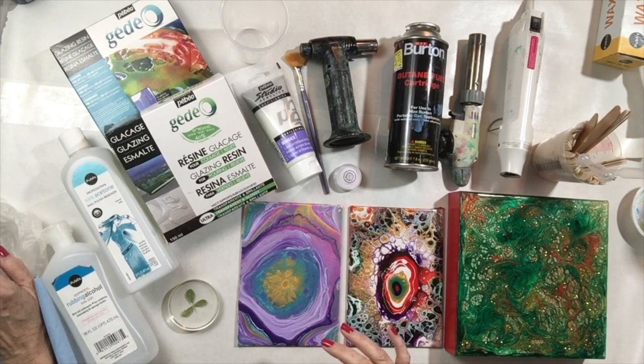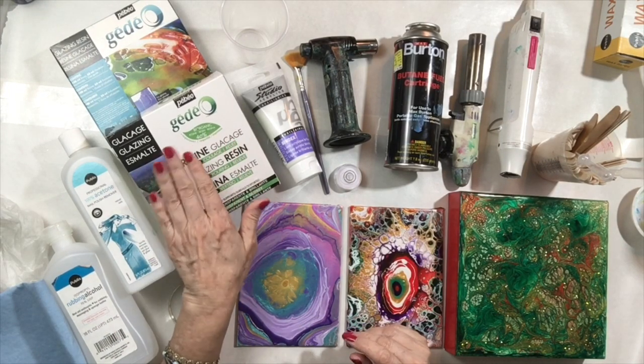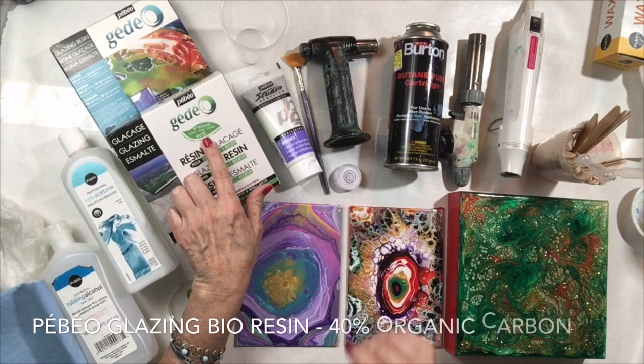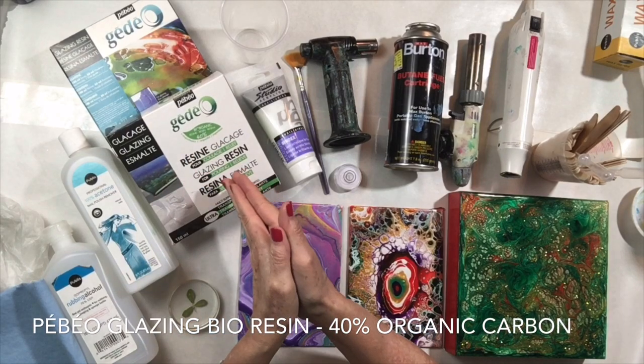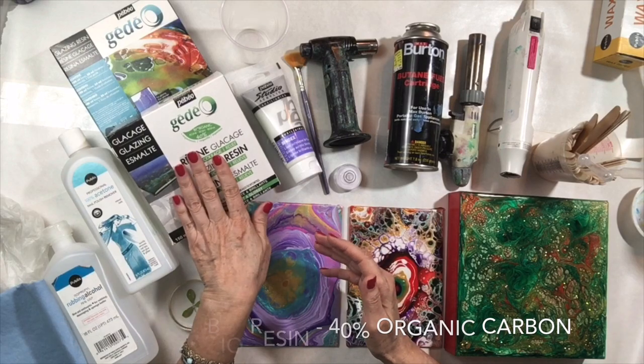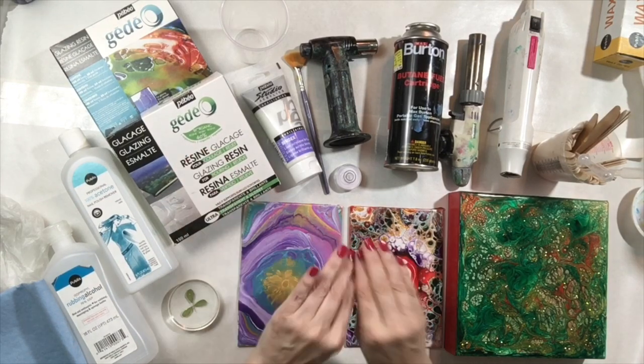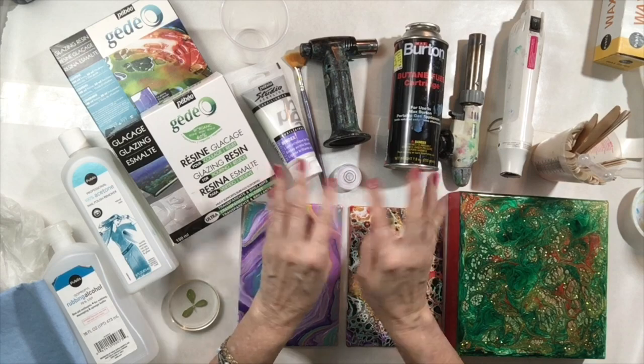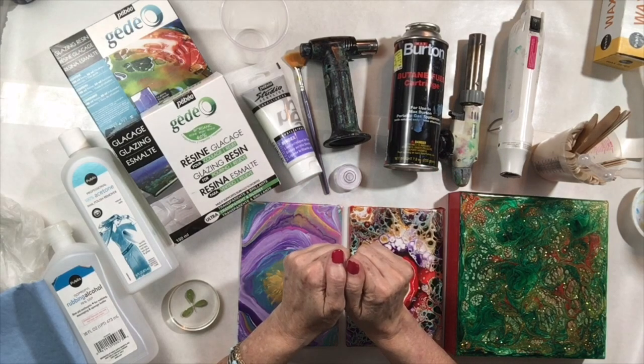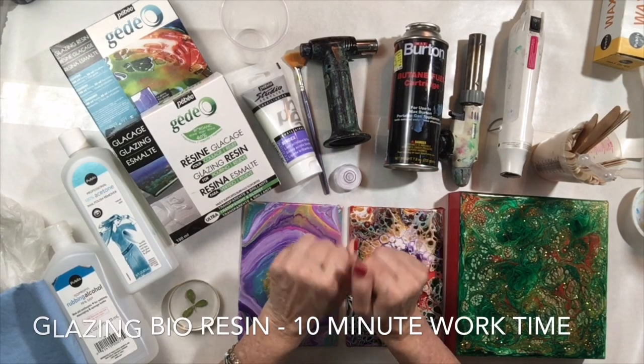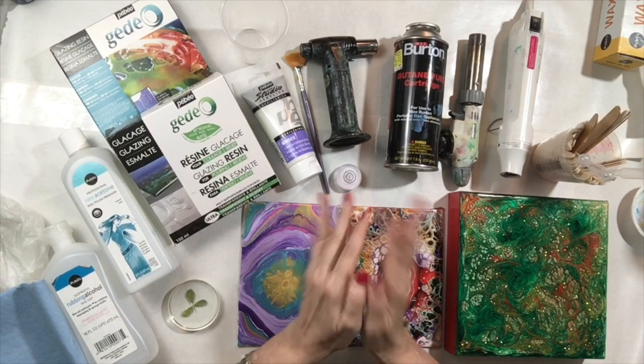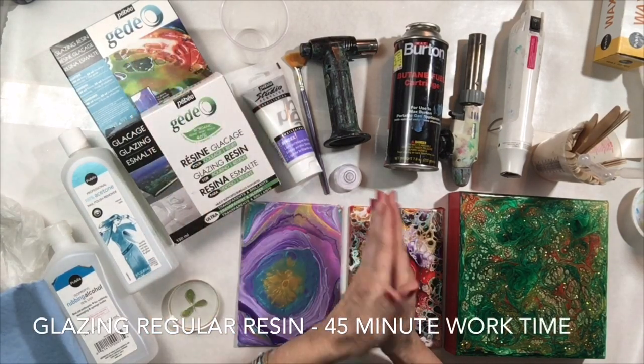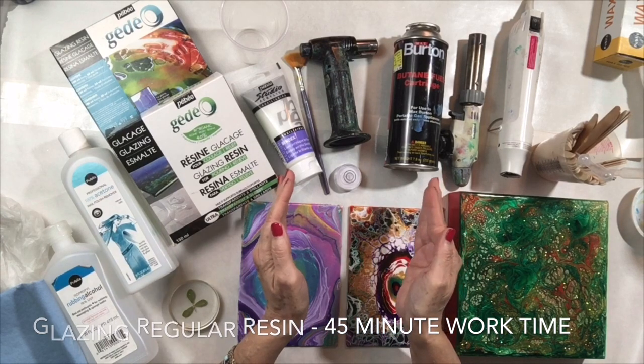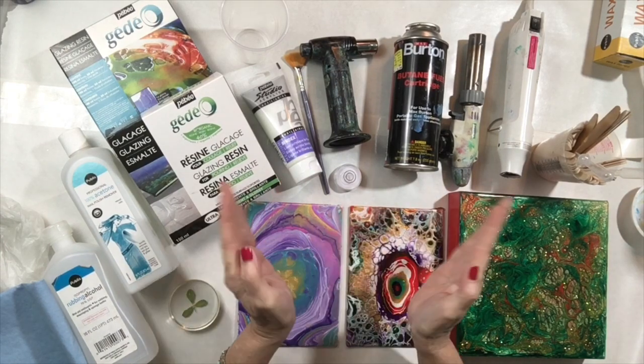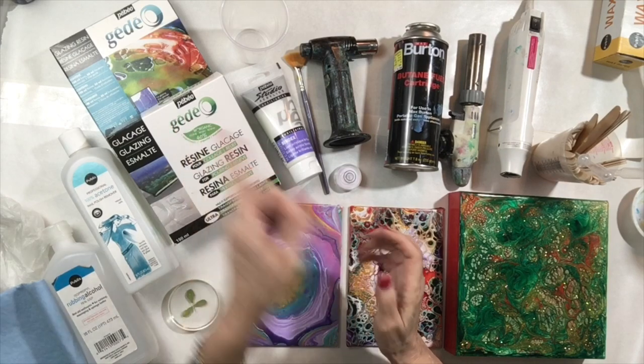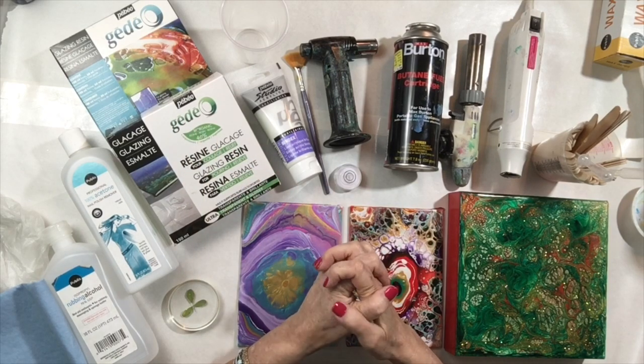Now, there are two types of glazing resin from Pebeo. One is the bio-resin. What's nice about this is 40% of it is organic carbon. This bio-resin is excellent for coating, and it's thick enough it'll go to the edges and it'll give you that nice rounded edge. The bio-resin will set up in about 10 minutes. If you need more working time, then the original glazing resin from Pebeo has about a 45-minute work time. So for larger surfaces, you may want to consider the original Pebeo glazing resin.